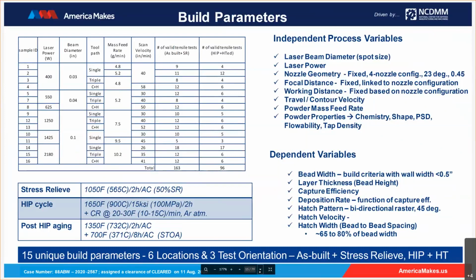For example, with increasing laser power, the beam diameter and the feed rate may need to be increased. And this can be unavoidable. So for the wall feature, a total of 15 unique combinations of process parameter values were chosen. To highlight that, the table here shows some of the principal variables. Now, for the bounds of these process variables, we chose a sizable range of the machine and process capability, and parameters were varied at different stages of the planning, building, sampling, and characterization.